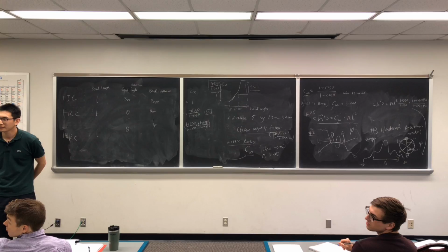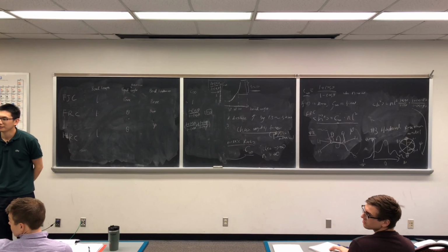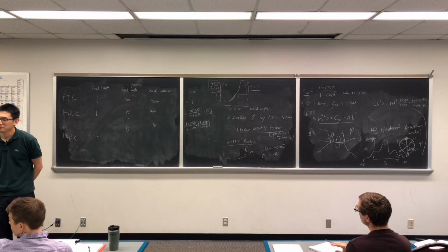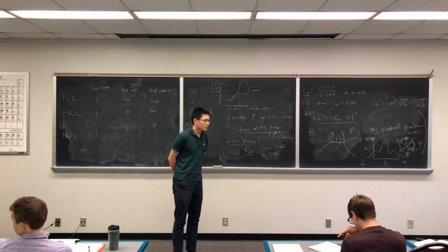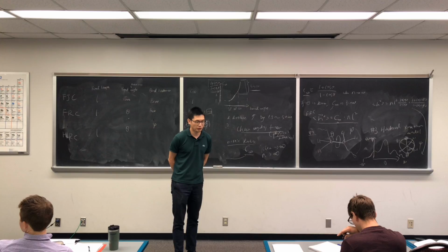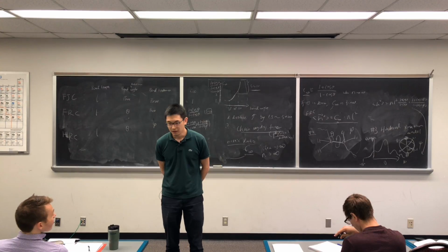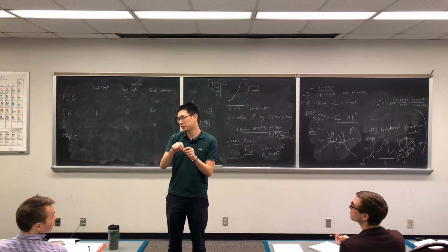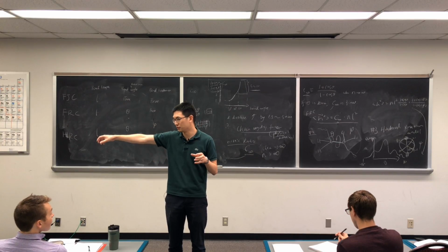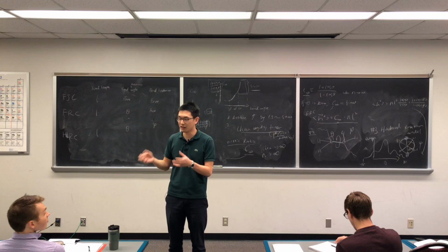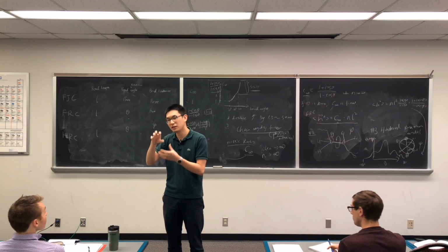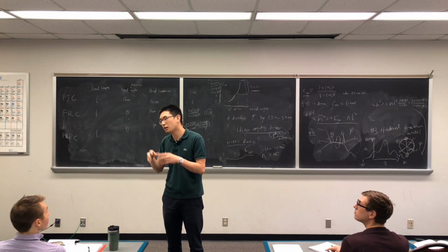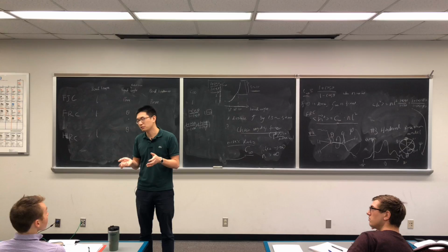So you said our first conclusion was that it would increase the distance by 1.5 to 3 times, for C theta, or C infinity. Next, on your table, you wrote about 3 to 10 times. So that will depend on the real bond. Think about the case where it's not a very simple carbon-carbon bond all the way. Now you have something hanging out, as in polystyrene, for example. The backbone is still a carbon-carbon bond, but you have a dangling group coming out. These will come into play in how they affect the characteristic ratio.